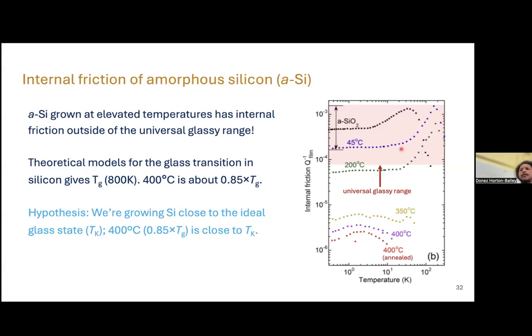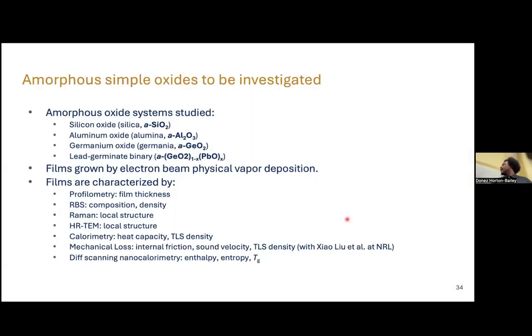So looking at some previous work from our group, the range is not here at all. So there's like a pink range between 10 to the minus 4 and 10 to the minus 3. We saw that with increasing deposition temperature, the vapor deposition temperature of the substrate, we're able to actually decrease this plateau below the universal range. And so our group with amorphous silicon, so not silicon dioxide, but just pure silicon, we were able to see that it is possible that these states do exist, that this idea of an ideal glass, a glass that has much fewer TLS than a typical glass, we're able to actually see this at high growth temperatures. All right, that slide is in the wrong place.